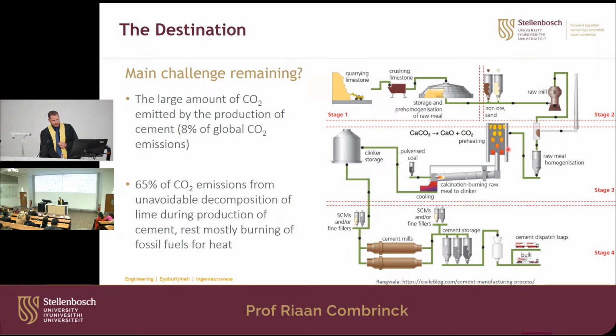Now the problem is once you heat this limestone, which is calcium carbonate, there's a chemical reaction where it goes to calcium oxide and CO2. So there's the main culprit. There's the problem. That CO2 is given off just by the chemical reaction. So we haven't even come to the heating with fossil fuels to get to 1,400 degrees Celsius. So that is the big problem. That is the elephant in the room for concrete and cement production specifically.